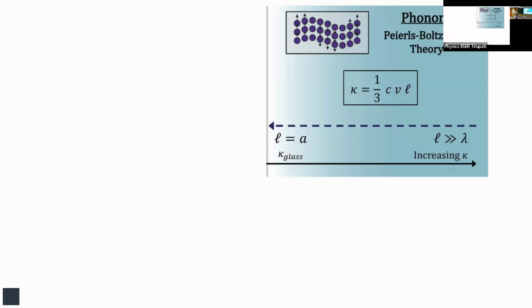Phonons are going to carry the heat. Phonons are, as you know, atomic vibrations, coherent vibrations of atoms through the lattice. And if these, while they're carrying the heat, get scattered, the information will not get carried. So if the heat-carrying acoustic phonons get scattered very much, thermal conductivity will go down. And if the phonons are very fast and going very beautifully without being scattered, the thermal conductivity would be large. So the question is, how efficiently can I scatter? If I want low thermal conductivity, how efficiently can I scatter the phonons?